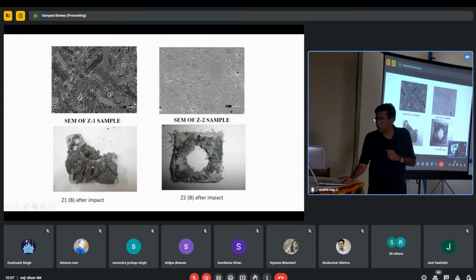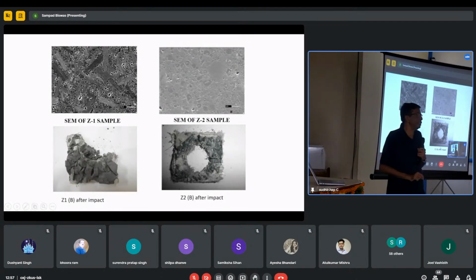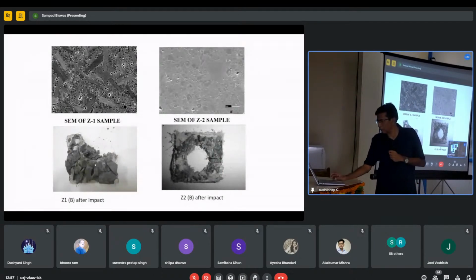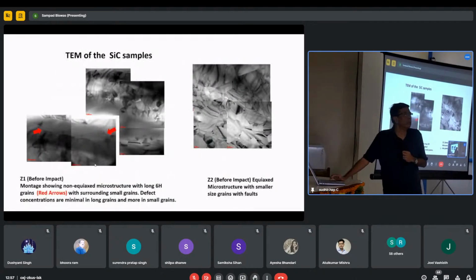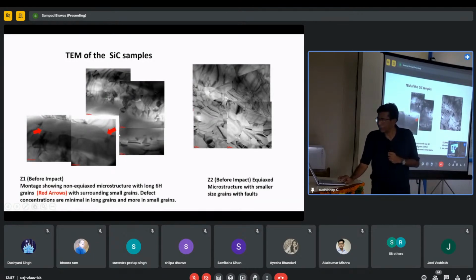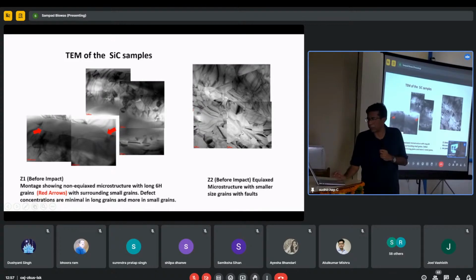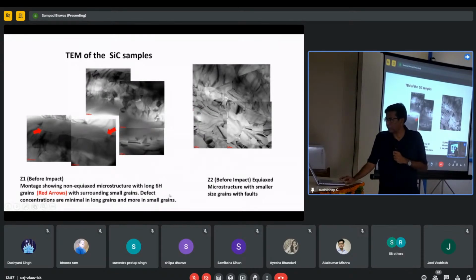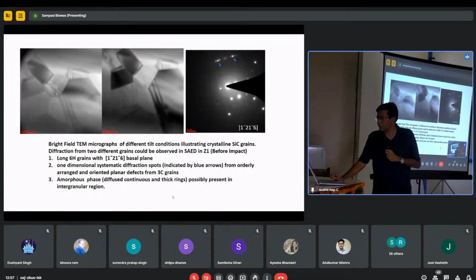So we took out the fragments near the bullet hit region, and we then carried out sections for the TEM analysis. In this TEM analysis, you can find this is a very long grain I wanted to show you, and these are very small grains attached with it. In the other case, it is very smaller grains. What I wanted to show you is that the surrounding small grains are also very important. It has got a lot of defects, and these defects have been analyzed here.